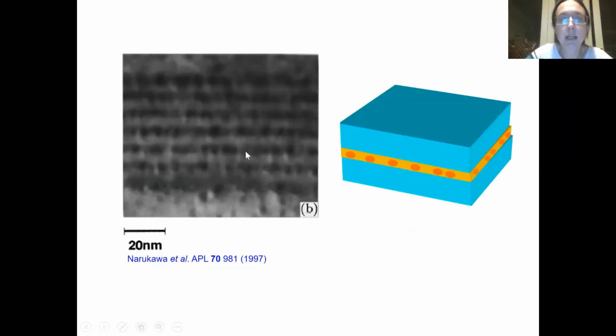Now, these are some of the really early pictures that were taken of indium gallium nitride quantum wells using an electron microscope. And you can see that the quantum wells look really quite blobby. And people interpreted that blobbiness as being linked to these changes in indium content that we said might be the key to understanding why these devices work. And everyone was like, aha, now we understand there are these changes in indium content. That's why these devices work. We'll engineer better changes in indium content. That's the way forward to make the devices even better. The problem was that that wasn't really the end of the story.